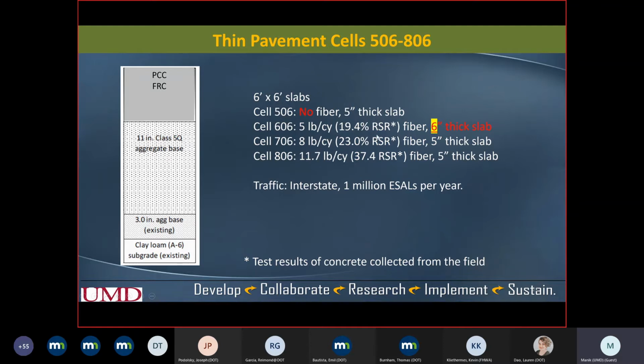And this residual strength ratio reported is from the ASTM C1609 test we did on beams prepared at the site. We brought them to the lab, or they were given to us in the lab, and then we tested them. Again, a little bit of reminding about the structure. Right under the slab, we had 11 inches of class 5Q aggregate base. The last one for cells 139 and 239 was 6 inches. Now it is 11 inches, you can see, and it makes sense. It's on the interstate.